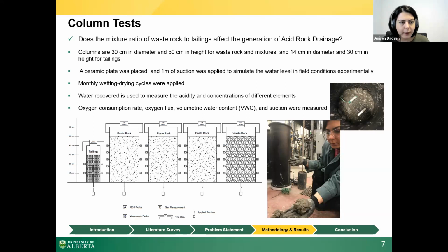Our columns were instrumented to measure oxygen consumption rate, oxygen flux, volumetric water content, and suction. There was a monthly cycle of wetting and drying. We added 10 liters of water to the waste rock and mixture columns, the big ones, and 2 liters of water to the tailings column to replicate field condition in the humid climate. Also, we used the water recovered from the columns to measure the acidity and concentration of different elements.